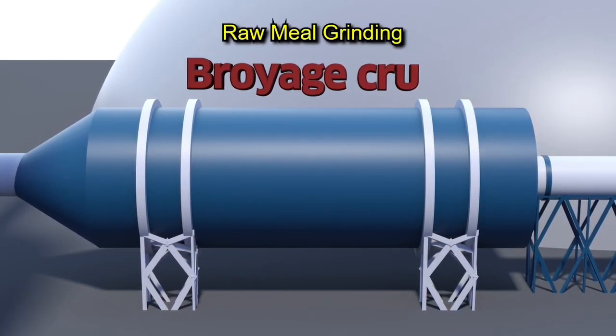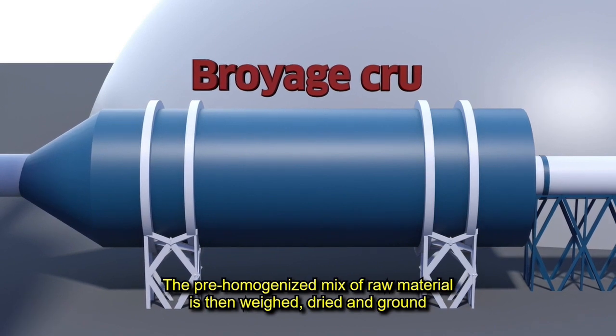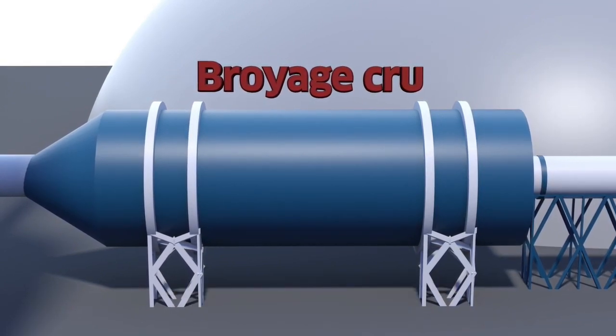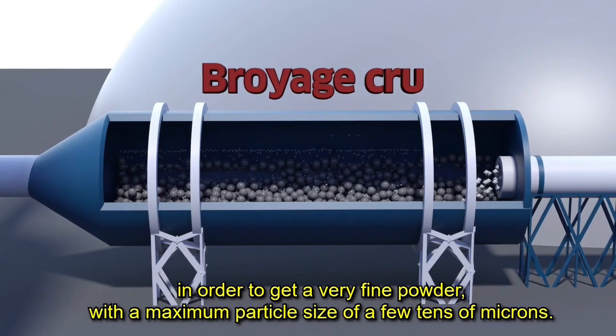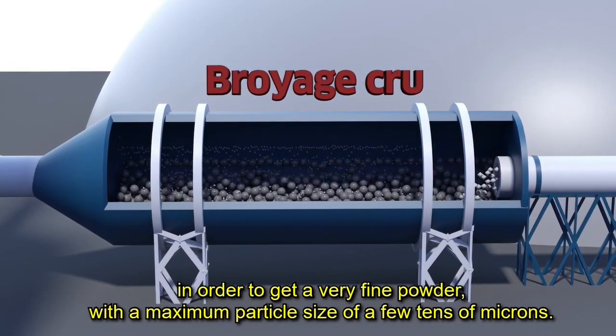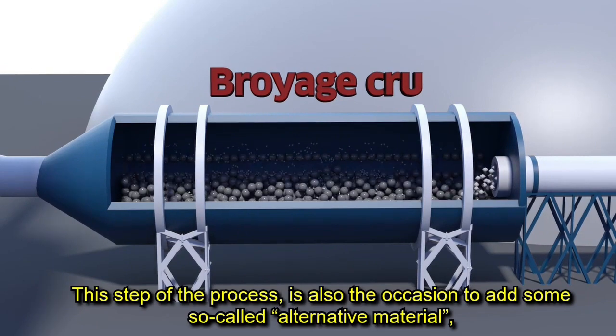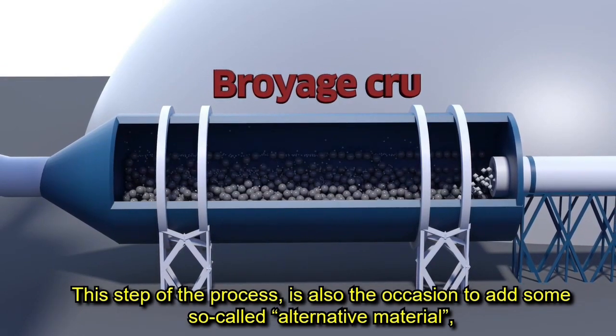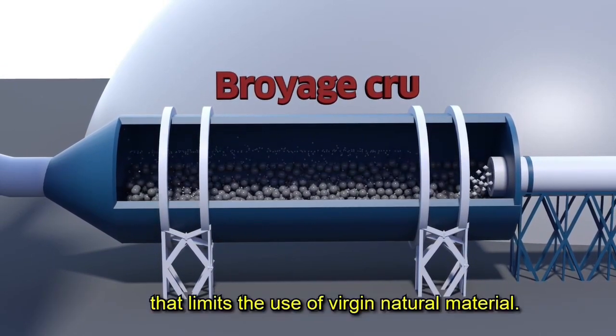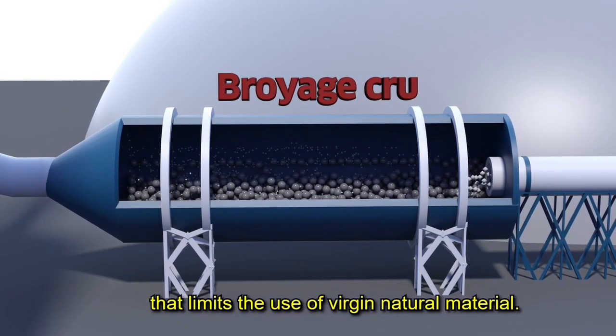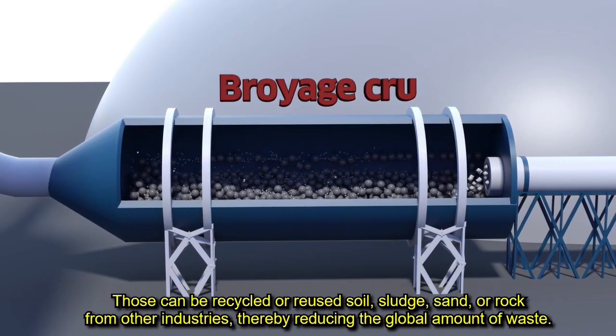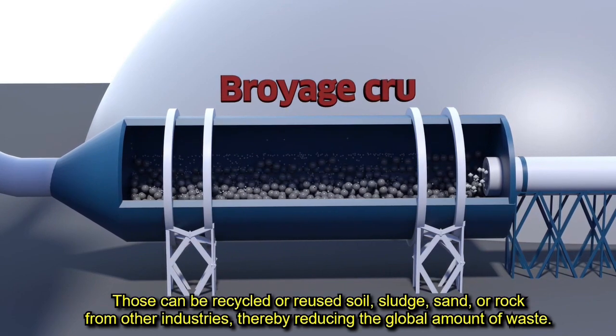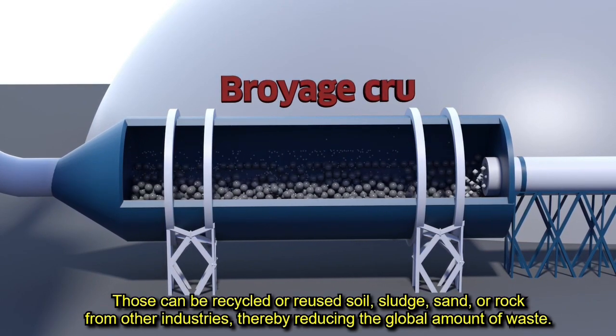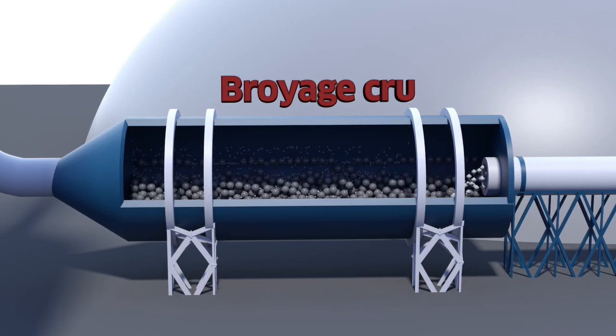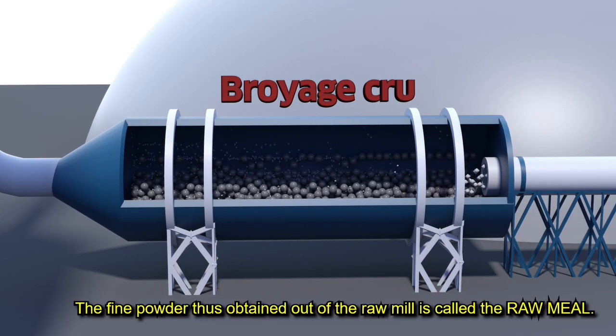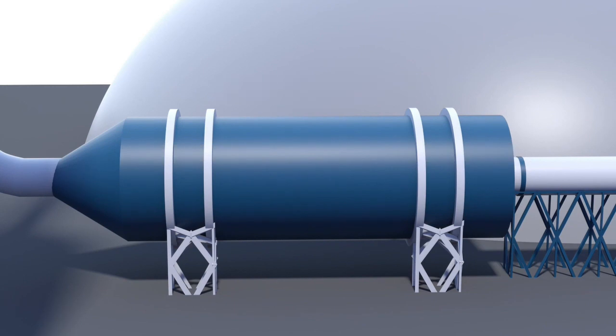Raw meal grinding. The prehomogenized mix of raw material is then weighed, dried and ground in order to get a very fine powder with a maximum particle size of a few tens of microns. This step of the process is also the occasion to add some so-called alternative material that limits the use of virgin natural material. Those can be recycled or reused soil, sludge, sands or rocks from other industries, thereby reducing the global amount of waste. The fine powder thus obtained out of the raw mill is called the raw meal.